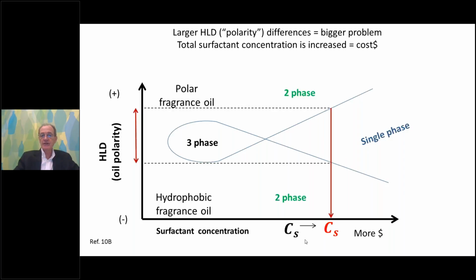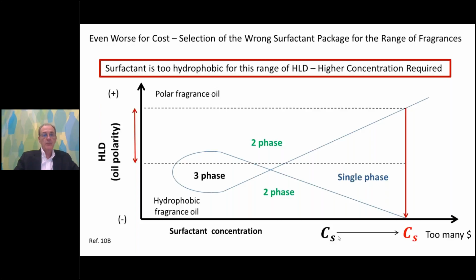However, in the real world, that's usually not the case. Fragrance oils especially can display a rather wide range of EACN, which means they can exhibit a pretty wide range in HLD for the single surfactant blend we're trying to use. What happens there? We have to turn up the concentration of the surfactant that we're using. More dollars, increased cost. The worst situation though would be if we pick a surfactant package that is overall too hydrophobic for the HLD range of the oils we're trying to deliver. Now, this mismatch is so large, I have to crank up my surfactant concentration quite a bit, and we go from some dollars to too many dollars in the development of our lotion.